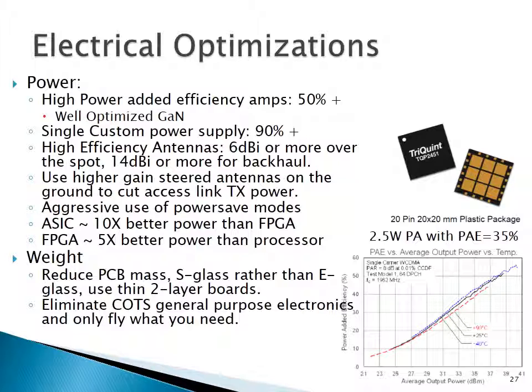Weight is secondary on the electrical stuff, but you want to reduce the PCB mass, the weight of the printed circuit boards. You can steal a lot of techniques from the space guys here, and use thin S glass rather than E glass, and you don't have to use glass epoxy. There are other resins that are lighter. You can just do two-sided boards. If you can avoid using multi-layer boards, then just go two-sided and make them as thin as possible. And then again, do away with commercial off the shelf, because if you do commercial off the shelf, then you inherit the electrical designs and the poor weight and power efficiencies of whatever that vendor is.